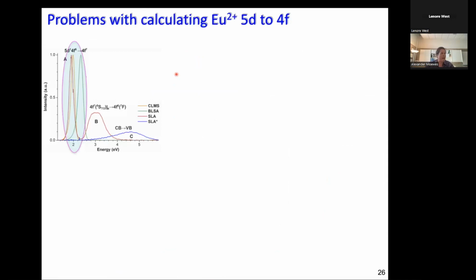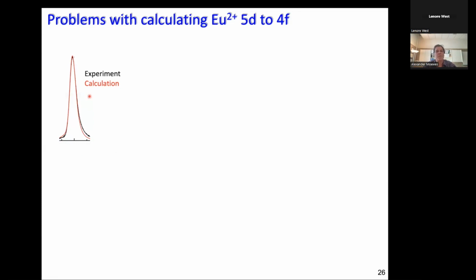Now I wanted to spend 5 minutes on one other interesting problem, and that sharpens your senses a little bit about luminescence materials. So again, you have seen this graph a moment ago. These three features here are again the 5d to 4f emission lines, very narrow, tunable through the choice of host lattice. That's all really great. And now what we ideally want to do is also calculate these. Now, the problem is we are only interested in these peaks, and anybody who has ever tried to do a calculation knows this is what we essentially want to do.